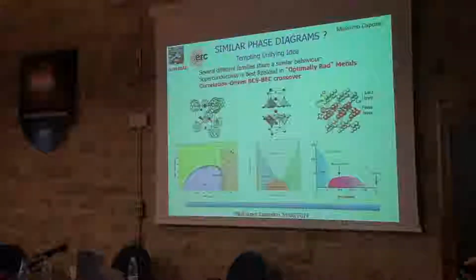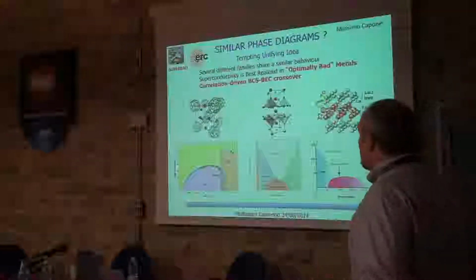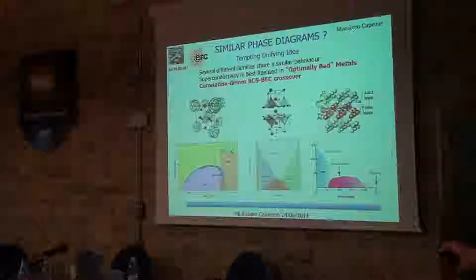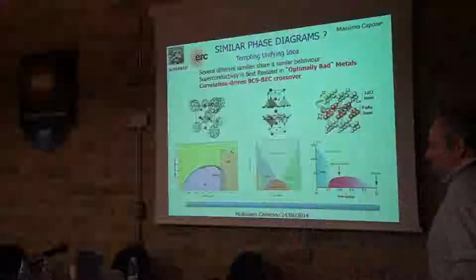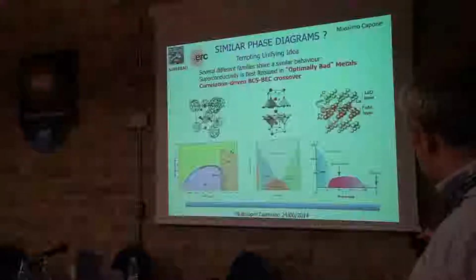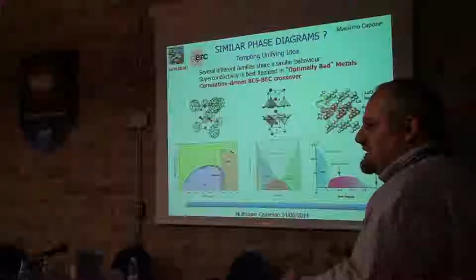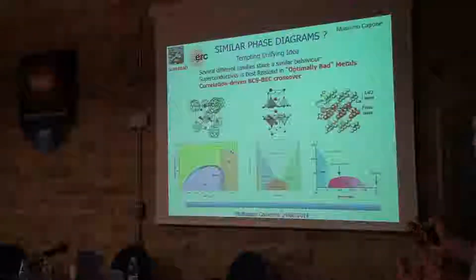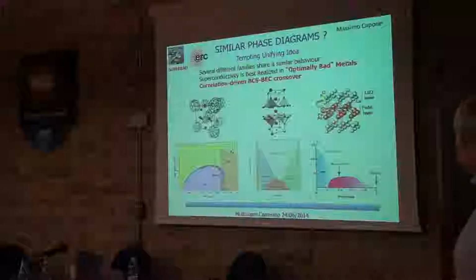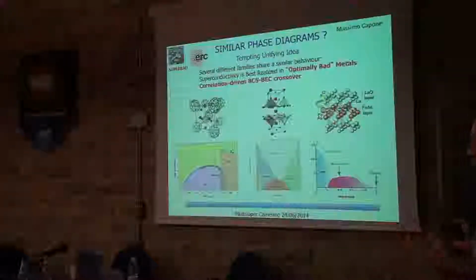The two that I mentioned here, I mentioned a less known member of the family, which are the alkali doped fullerides, and I can also put, for example, the heavy fermion materials. So we may really hope for a sort of universal way to understand superconductivity in non-standard materials, and that superconductivity appears when we are at some ideal distance from this insulating or bad metallic state. There is an optimally bad metal, which is a link that I'm not going to discuss here, and the general picture may be of a correlation-driven BCS to BEC crossover, going from the overdoped side to the underdoped side.